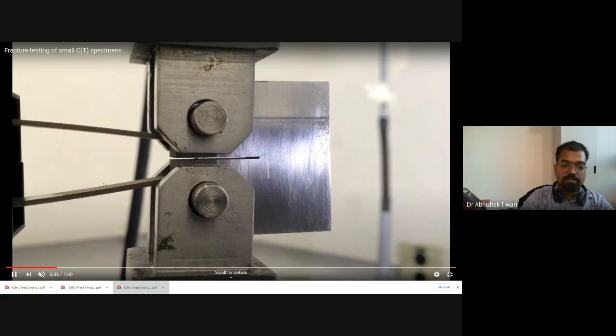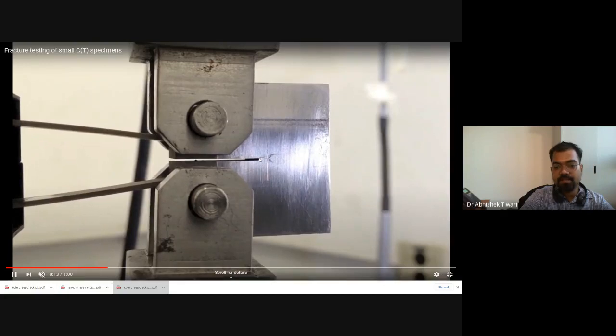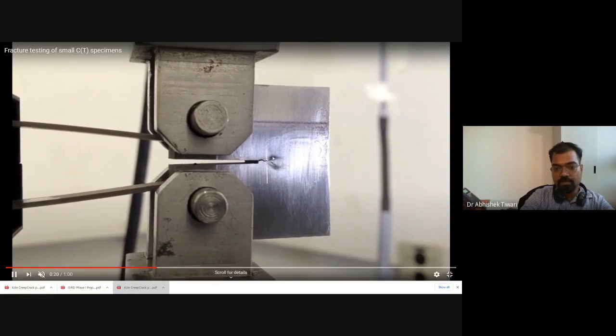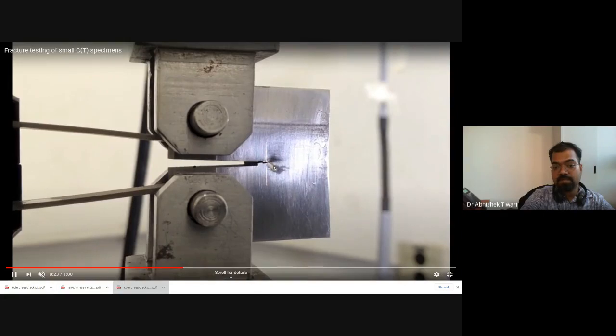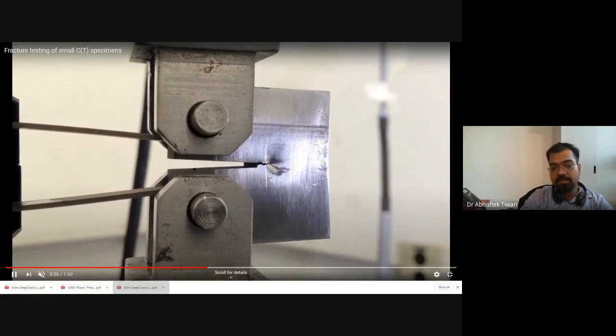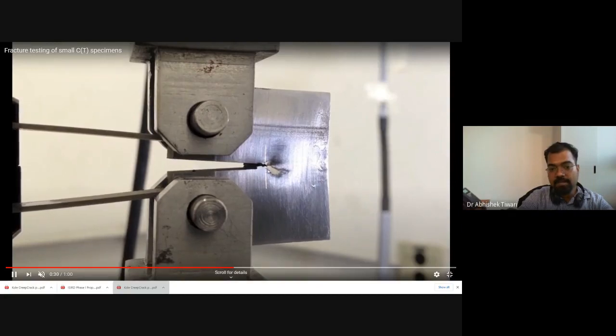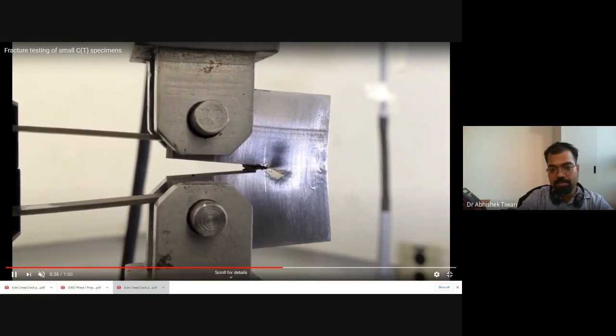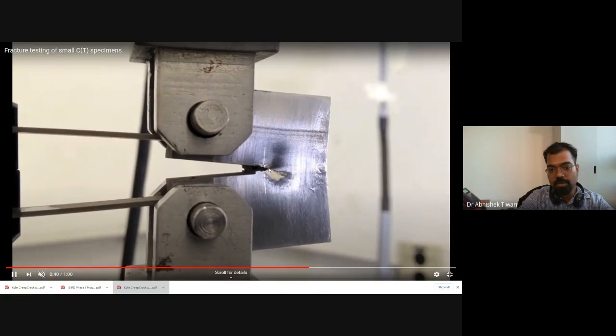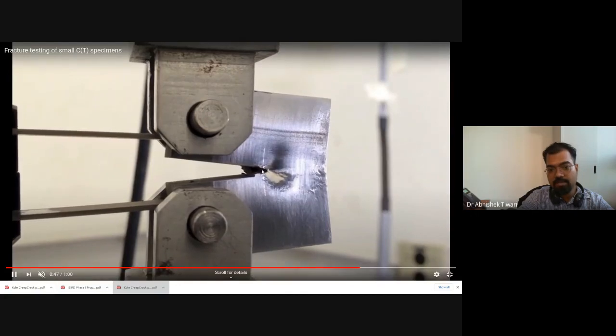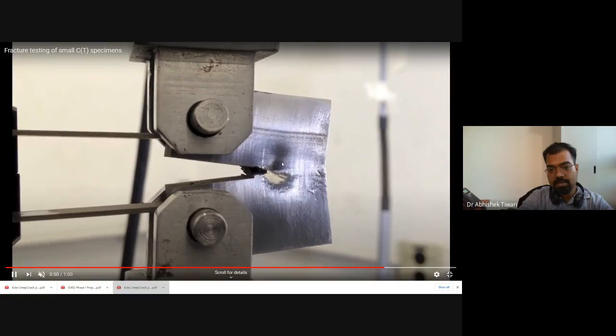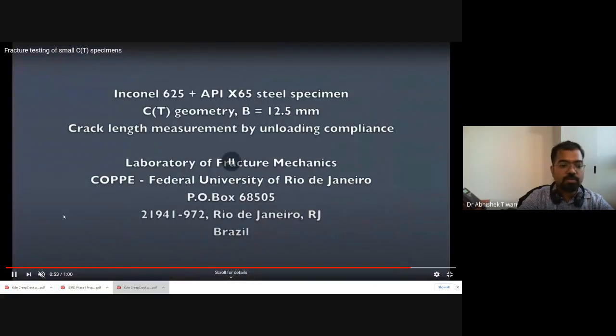So if I run this video, you see this is cyclically loaded. Now you see there is a crack. The crack has opened up to here. And you see these are plastic zones. That dip is because of the plane stress condition at the surface, and that material is sinking in. And you see that the crack is opening after heavy deformation there. From this point beyond, it is not opening much. But the opening will be more inside in comparison to outside. You see, this area is completely deformed.